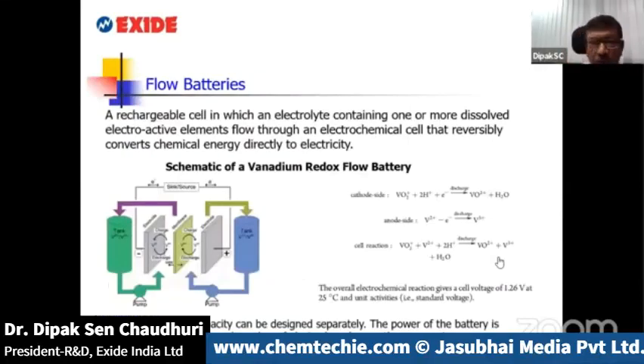Now, flow battery is a very interesting consideration where the basic electrodes are in the liquid form. And the electrode materials in the liquid form are pumped from two individual tanks, put into an electrode where they electrochemically react. And as I told you, they release the electrons which go into the external circuit. One of the major advantages of the flow batteries is, of course, that you can completely segregate power and energy, because power comes from the total dimensions of the electrodes and total energy comes from the volume of the reactants in the tank. So if you just want to increase the power without changing the energy, you can increase the membranes of the electrodes in between. Or if you want a higher energy throughput, you just need to replace it with larger tanks.